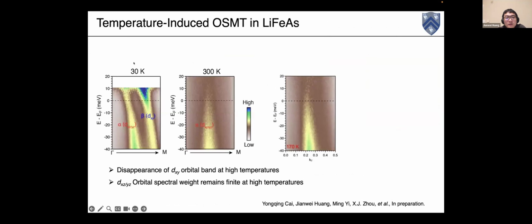So then we did our data up to 300 Kelvin. This is the low temperature data at 30 Kelvin and the high temperature data at 300 Kelvin. And actually, we surprisingly find that the XZ/YZ orbital band remains, but the XY orbital completely disappears. You can see it more clearly from this animation here.